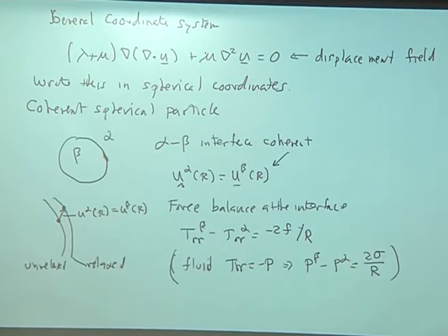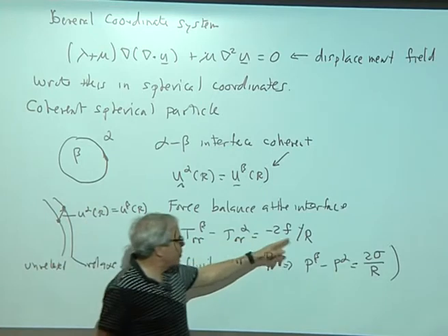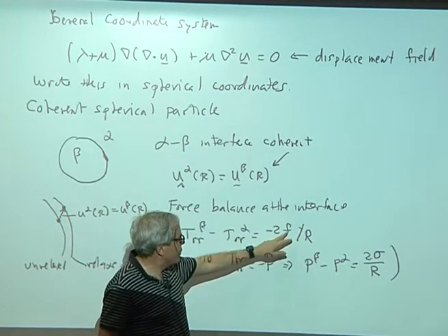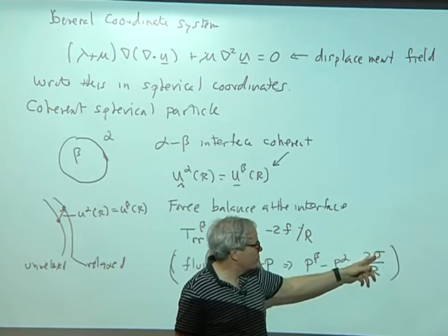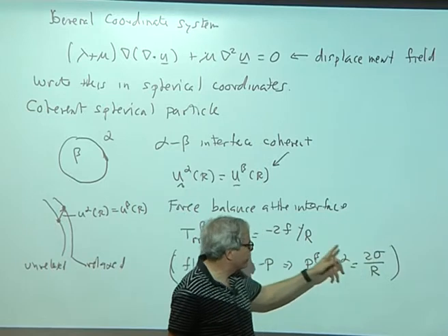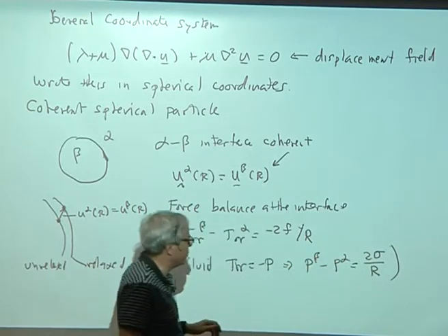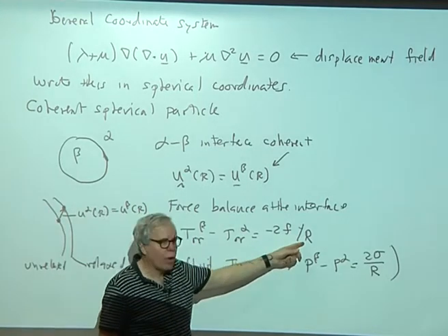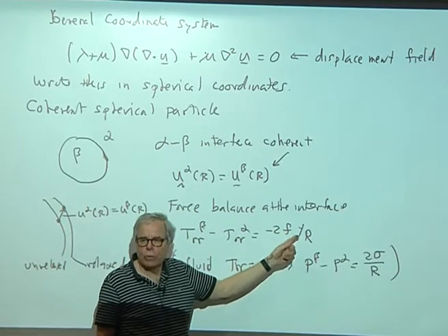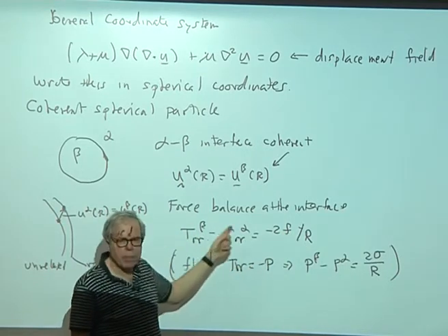Okay. So you have this excess force. Oh yeah, I should mention one thing. This is kind of an interesting thing. So this goes like the surface stress divided by R, right? If you say that the surface stress is about equal to the surface tension, typical surface tension, like 1 joule per meter squared, kind of an interfacial energy, 1,000 millijoules per meter squared. You notice this goes like 1 over R. So I can always choose an R small enough such that these stresses can be big due to this thing, right?